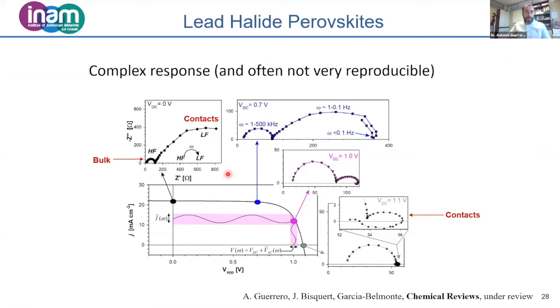If we go to a different applied DC bias, 0.7 volts, here we see how the size of the arcs is reducing. So here we have one arc with about 100 ohms, and the other one was 600, more or less, and now this is about 50. Here you see 50, and this is about 150.